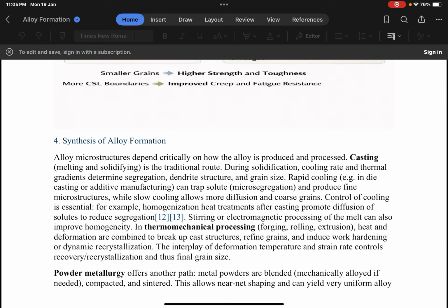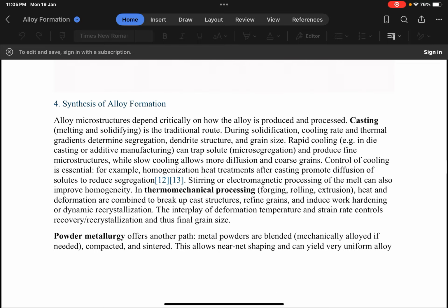Rapid cooling, for example in die casting or additive manufacturing, can trap solute, reduce micro segregation and produce fine microstructure, while slow cooling allows more diffusion and coarse grain. Control of cooling is essential. For example, homogenization heat treatments after casting promote diffusion of solutes to reduce segregation. Stirring or electromagnetic processing of the melt can also improve homogeneity.